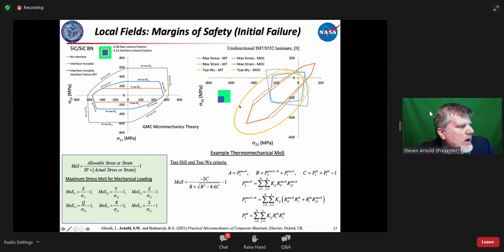And then now here on the right is a demonstration of the similar margins of safety curves, but here we're showing three different surfaces, where the blue is a max stress criterion, the orange is a max strain, and the yellow is a Tsai-Wu. And then the difference between the dotted and the solid lines are the difference in micromechanics theories, where the dotted are Mori-Tanaka and the solid is method of cells. And we actually have developed full thermomechanical margins of safety as well.